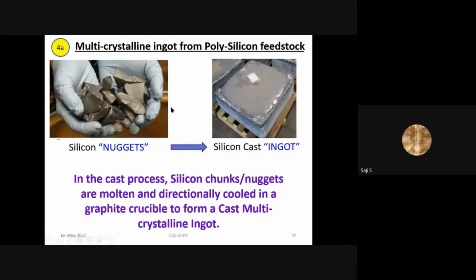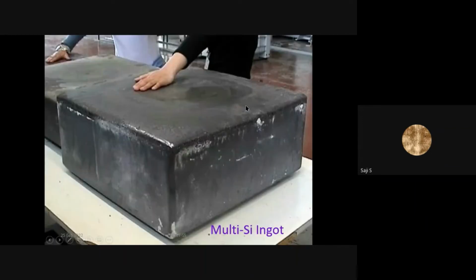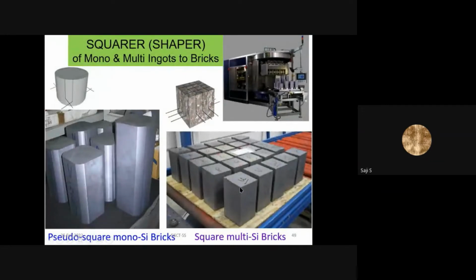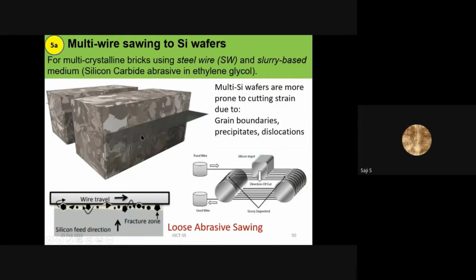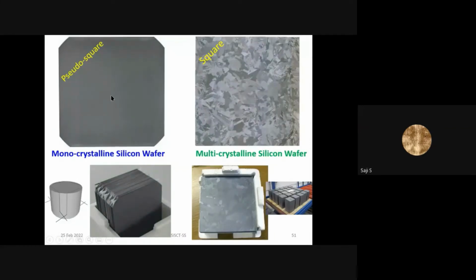Similarly, it can be grown into a multicrystalline ingot by directionally solidifying the molten polysilicon feedstock. So you get a large silicon cast ingot of this order, which is known as multi-silicon ingot. It's almost about 1,000 kg each ingot, and this can be squared, cut into small bricks. Both monocrystalline and multicrystalline materials can be cut into bricks, and sawed or cut into wafers. There'll be a kerf loss by cutting because some of the material will be lost, but eventually by cutting this you get a monocrystalline wafer or a multicrystalline square. This is a pseudo square and this is a square wafer. So these are the two types of silicon popularly used for photovoltaics.